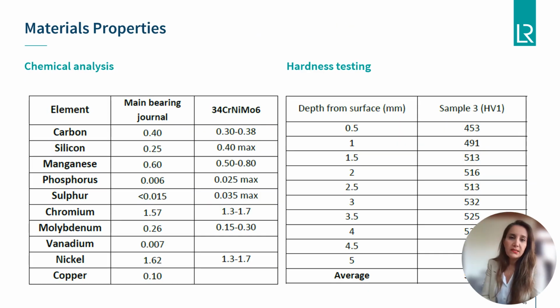For chemical analysis, a section was removed from the main bearing journal and analyzed by optical spectroscopy. The analysis was generally consistent with the grade, with the carbon level being marginally higher than the specified range. Vickers hardness testing and micro Vickers hardness testing was also conducted at the core and through the hardened layer of the main bearing journal, using a 10 kilogram load for Vickers hardness testing and 1 kilogram load for micro Vickers hardness testing. The results and the depth of the hardened layer were found to be consistent with that specified for this component.